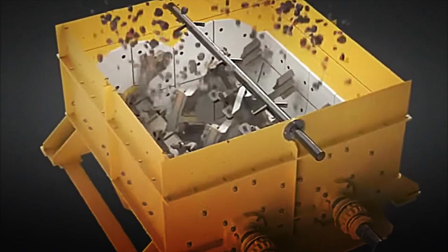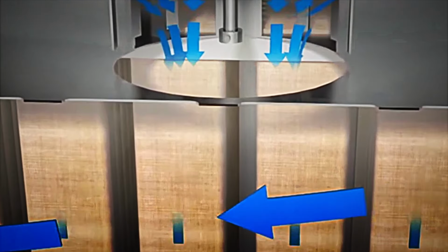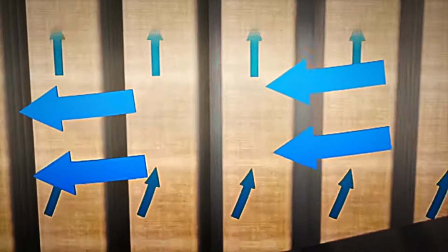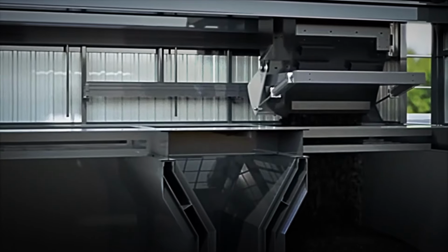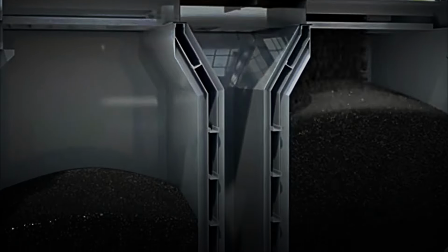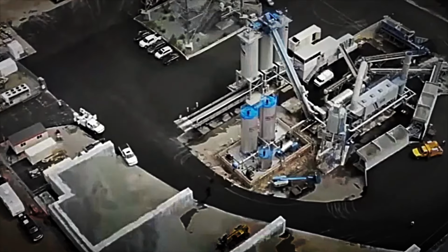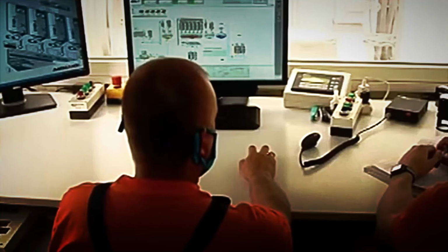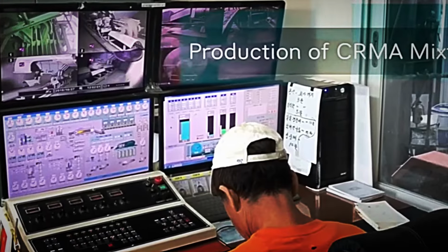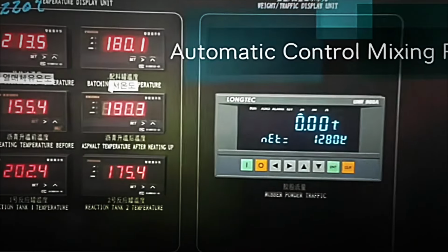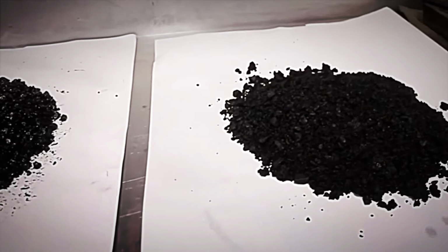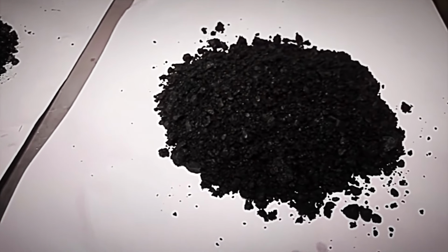After this treatment, the material proceeds to the phase where the true value of recycling is concentrated, its controlled incorporation into the bitumen. The bitumen is heated independently in special tanks until it reaches a homogeneous and stable liquid state, with temperatures typically ranging from 320 to 375 degrees. Once in these conditions, the crushed rubber is added in carefully controlled proportions, generally between 10 and 20% of the total weight of the binder, depending on the technical specifications of the asphalt to be produced.